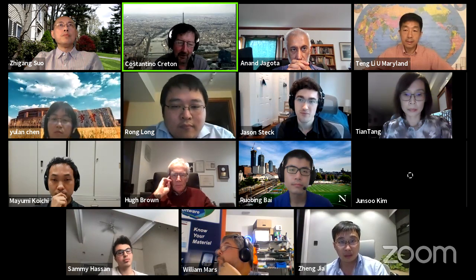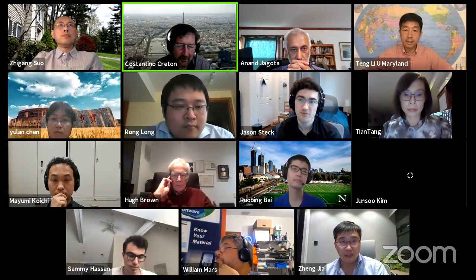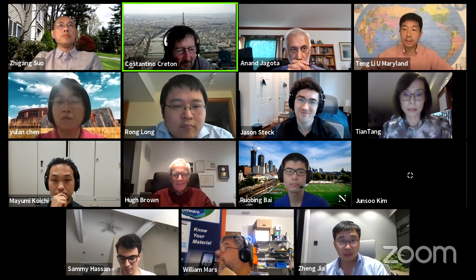In large deformation, which is where we are, where we start looking at activation, can you really ignore the connection between the chains? I don't know. I'm a little bit skeptical, but some results really seem to work very well. I've seen results in Jian Ping Gong's group on gels, where you look at the macroscopic measurement and what you would expect from a single molecule, and you get the same thing.